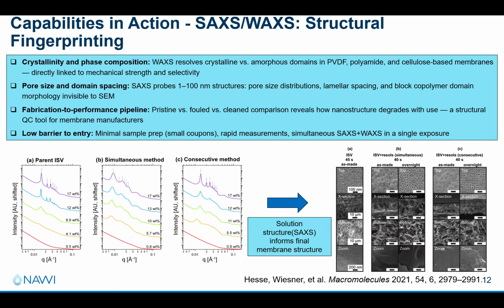Just some examples of data that you can acquire. So from SAXS and WAXS, you can get structural information. So you can get information about the crystallinity and the phase composition, pore sizes, fabrication to performance pipeline, pretty low barrier to entry for ex situ samples. And it is useful. So this is work from my graduate school work where we were looking at these polymer solutions for block copolymers. And we saw that depending on how you prepare the solution, you get very, very different membrane top surfaces. And so what this lets you do is you can take the data that you get with these SAXS WAXS techniques and inform the fabrication process later on. So that's just one example.